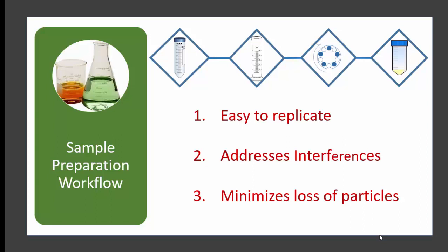If you have an aggressive sample preparation scheme, and it's overly aggressive, even just stirring the sample overly aggressively, one particle could break into 2, 3, multiple particles, and then numerically you're overcounting those particles. So we want to keep that in mind as well.